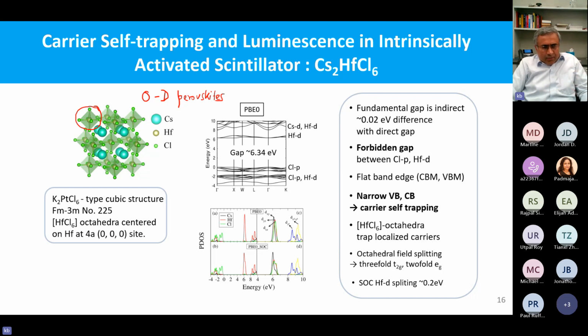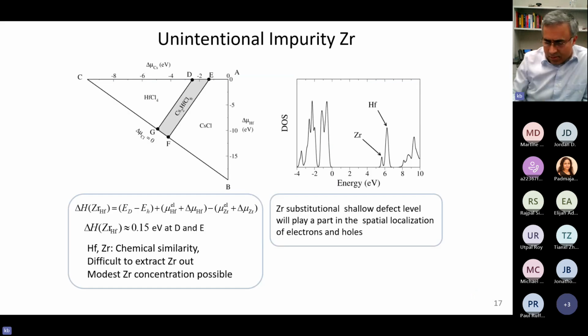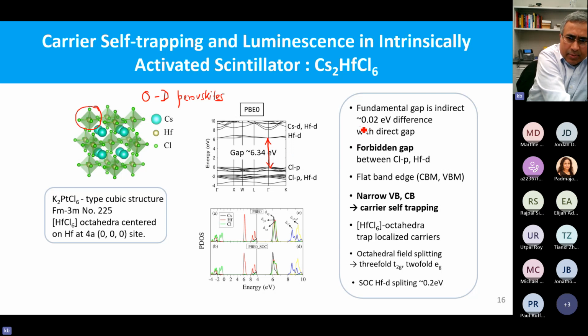Again, we start with the structure, we optimize the structure, make sure we have the geometry with the lowest energy possible, and then we call it an optimized geometry. Once we have that, we are ready to look into the electronic structure of these materials. For example, this would be the electronic band structure, which gives us a band gap at the gamma point of about 6.3 electron volt. The fundamental gap is a little bit less than that. The fundamental gap would be indirect, let's say 6.32. But at the gamma point, the gap is as stated.